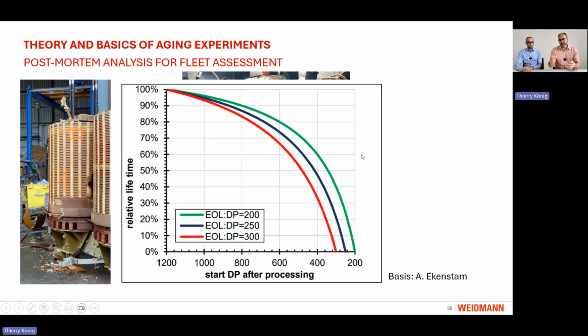You can go then into this graph, which was made by reformulation of the Arrhenius equation. Let's assume that you measure a dP of 600 at your insulation. You calculate with an end-of-life criteria of 200. So you go up here at 600 to the green curve. And what you get is that your relative lifetime or remaining lifetime of the transformer is still 80%.